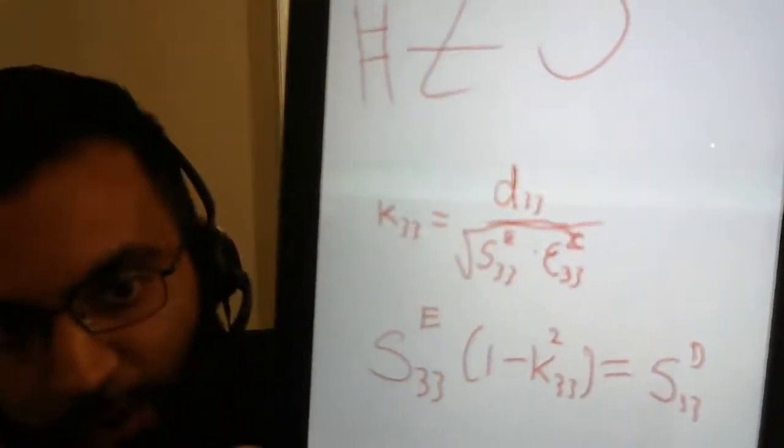I feel like you usually get a lower coupling factor than you would expect experimentally, but it's not so important to match the coupling factor once you have assembled your device, because it's going to be different for a lot of reasons. A lot of things regarding interfaces also affect the coupling factor. They're not exactly piezoelectric per se, but as I showed in these equations, you can calculate a new coupling factor by changing the D33 coefficient, and you might assume the permittivity is the same, which is an assumption.